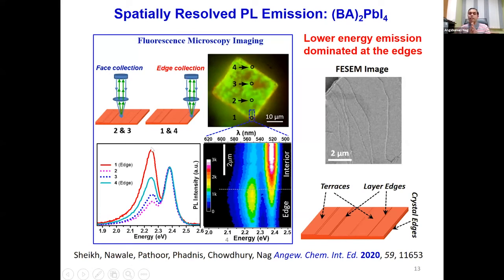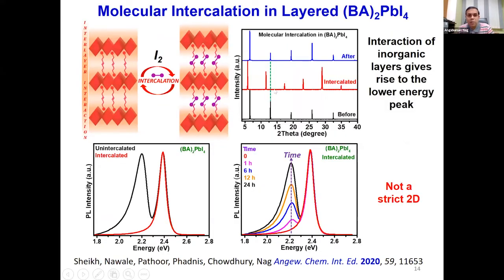So it looks like since at the layer edges the crystal structure is more flexible, probably the two inorganic layers come closer at the layer edges, and probably they interact to give rise to this new lower energy emission. To verify this hypothesis, we also did some intercalation.